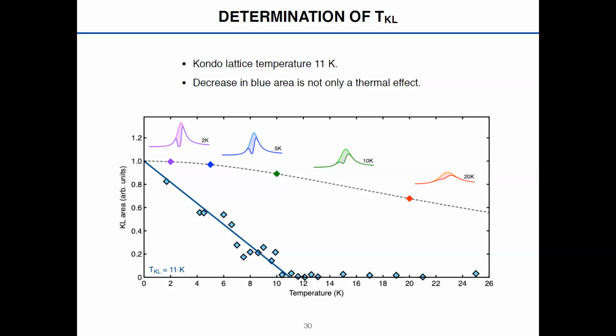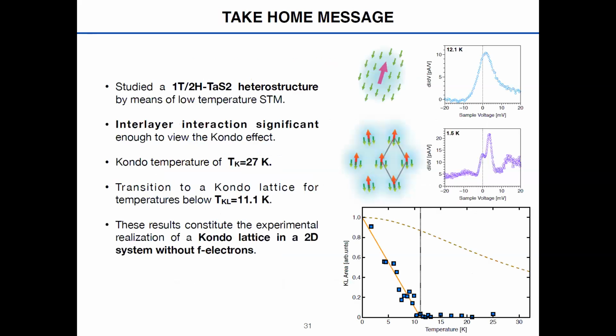To make sure of this, we've done a very simple model where you superpose a 3 millivolt gap with a Kondo resonance, and then you do the convolution with the Fermi-Dirac function just to broaden the gap with temperature. And this is the expected evolution of a gap broadening with temperature, and as you see, the behavior is quite good. Okay, so now I'll finish with the take-home messages.